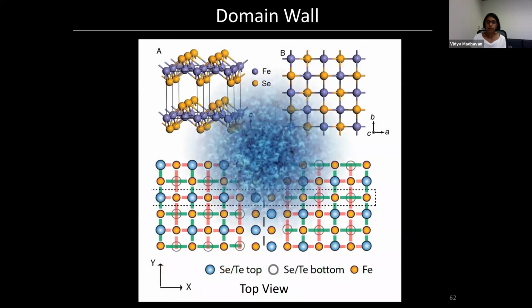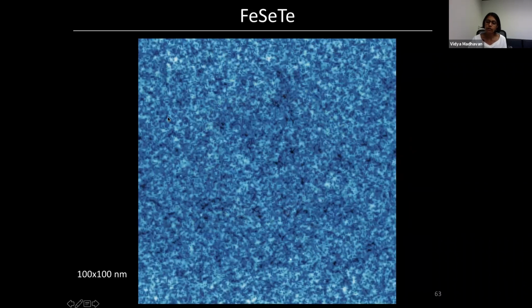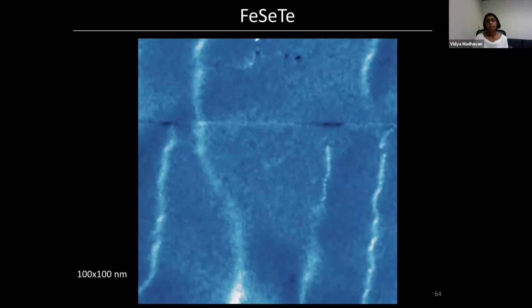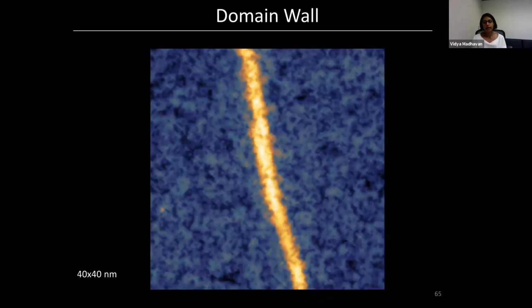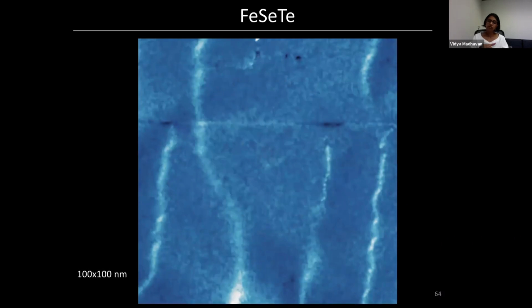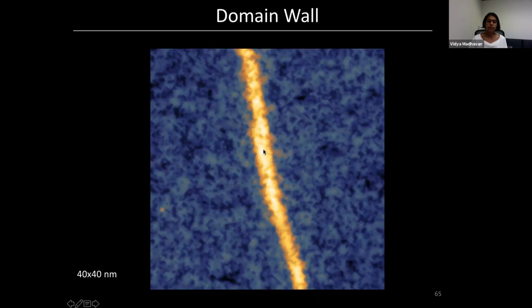So that's what we're looking for. A lot of the region of the sample looks really beautiful and pristine with no domain walls. But sometimes you can find regions with domain walls. And not all domain walls give you this pi phase shift. But you can go searching and you can find a domain wall where the crystal structure has kind of flipped, right? It's like a stacking fault.